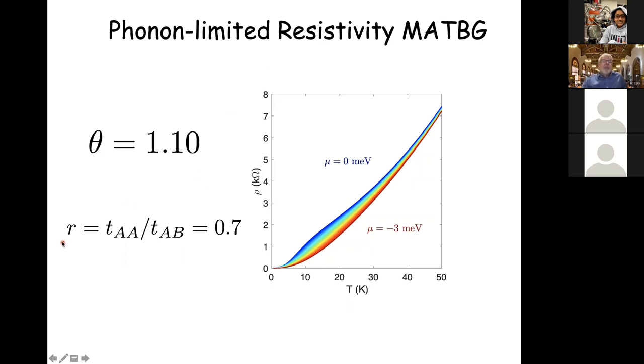This parameter here, R, has to do with the band structure model, the Moiré superlattice model with position-dependent interlayer tunneling that I explained to you before. And one thing I want to mention in passing is that it's clear that our original model wasn't perfect, and that you can refine it by, instead of having one parameter, allowing yourself one or two more. Turns out that hopping between layers in the same sublattice is a little weaker than between different sublattices. And so there's some uncertainty about the details of the band structure, but